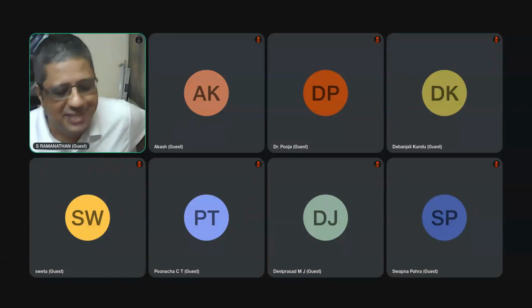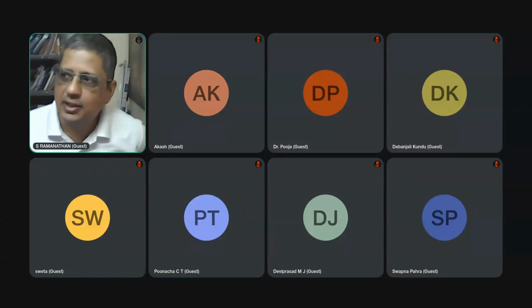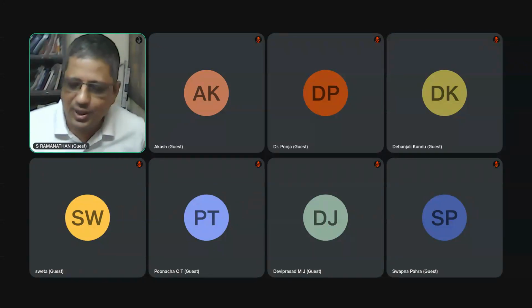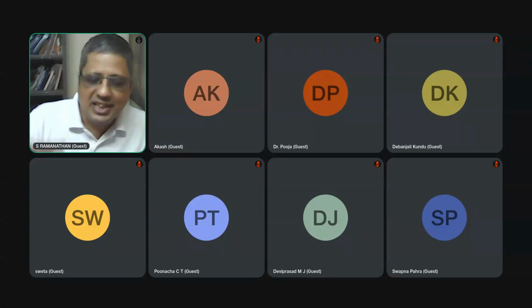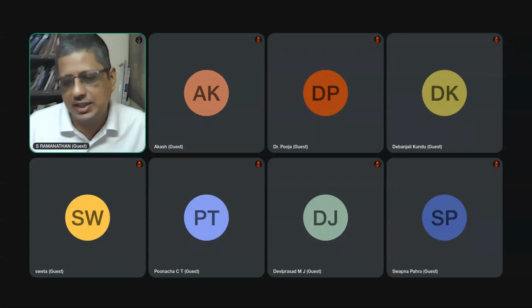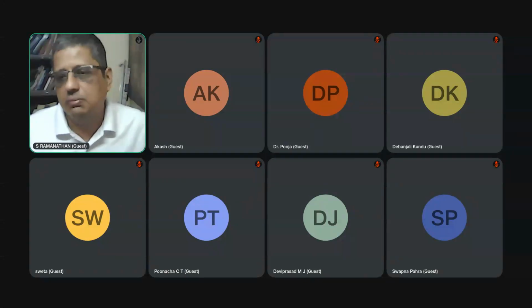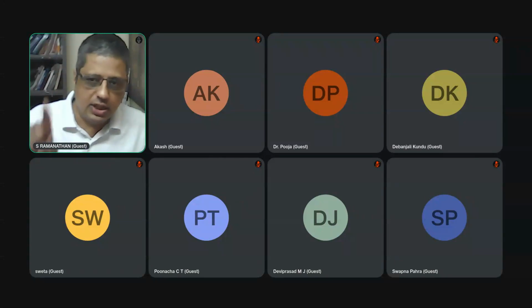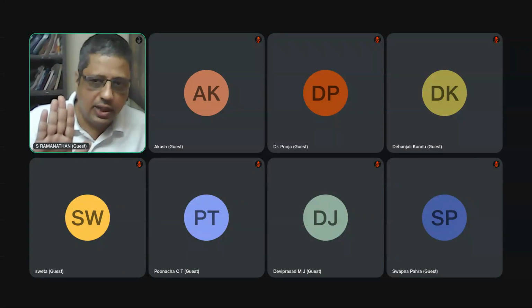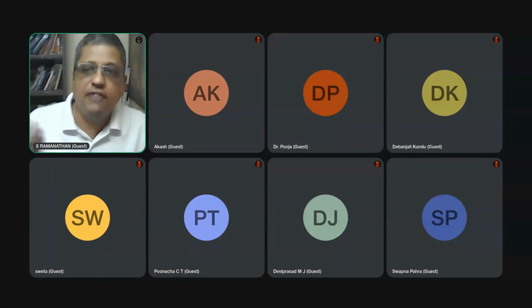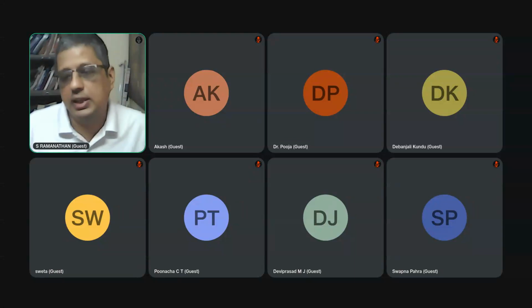What would be the approximate ratio? If you can give 10 to 1, we don't always give 10 to 1, at least 2 to 1. If not, at least 1 to 1. It depends on how much you can afford within the cell, how much space you have, constraints you have, etc. Within the constraint, if you give 10 to 1, beyond that there is no benefit. 2 to 1 is still okay. Going below 2 to 1, only if you really have to. Otherwise, keep it. And mesh can give you a large area. It's not the geometric area. I can give a platinum foil, or I can give a platinum mesh. For the same geometric area, mesh will give me more effective area. So you can use a mesh and gain more area.